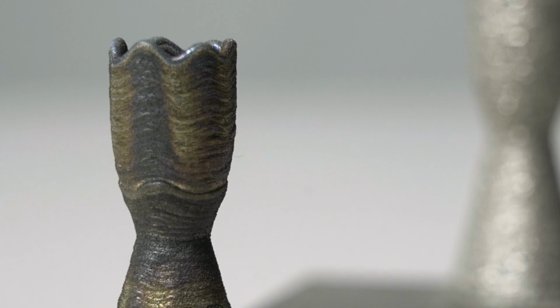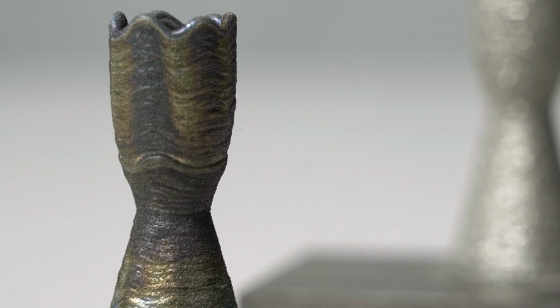You also look at where the differences start to occur. It's the necking section there. The amount of heat you're putting into a small cross section means there's less dwell time between this layer and the next. So you're adding more and more heat much more quickly as you start to neck down. You get this compounding effect that leads to differences in powder capture rate, which then leads to differences in layer height. In DED, what you're saying is the geometry of the part influences the heat transfer, which in turn influences how that part itself comes out.